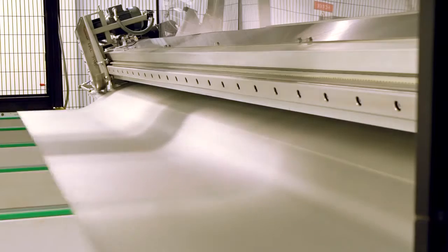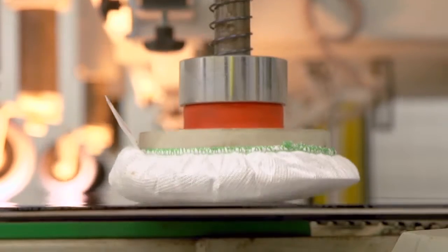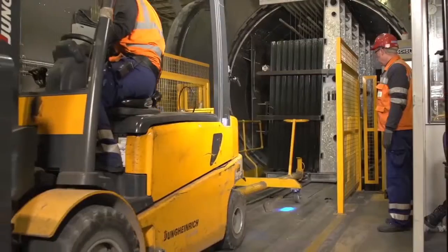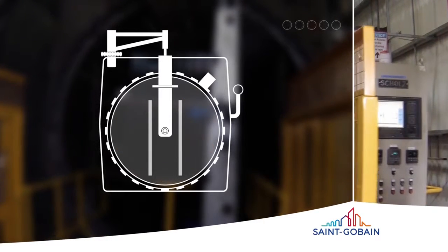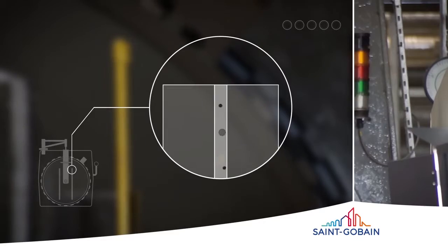Then, the PVB layer is sandwiched between two pieces of glass. To prevent bubbles from forming, rollers force air out of the PVB layer. The glass is now heated in an oven at up to 250 degrees Celsius to bond the PVB to the glass. Over several hours, the laminate is heated and cooled in a pressurized environment. This is the final stage of the bonding process, removing any remaining air bubbles.